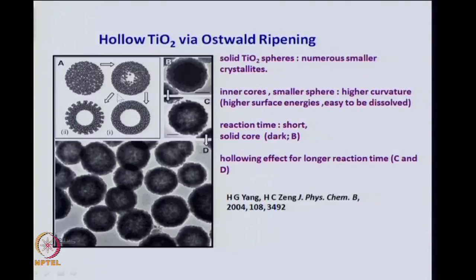And this is a model of what is happening in TiO2, how hollow TiO2 is forming. And these are real pictures where you see that the outer part of these large agglomerates of particles is becoming darker and the interior is becoming lighter. This is the hollowing effect which you observe because of Ostwald ripening at longer reaction time.